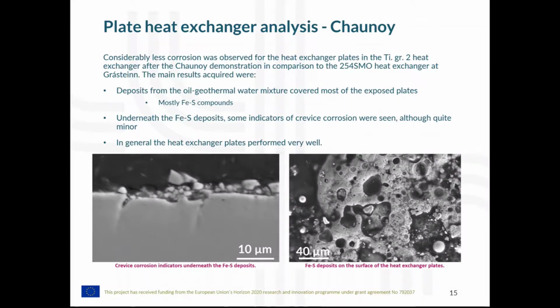And the main results that we acquired were that we have a mixture of deposits from the oil and precipitation of iron sulfur compounds on the surface of the titanium, which is something that we have seen previously in geothermal environments for titanium grade 2.